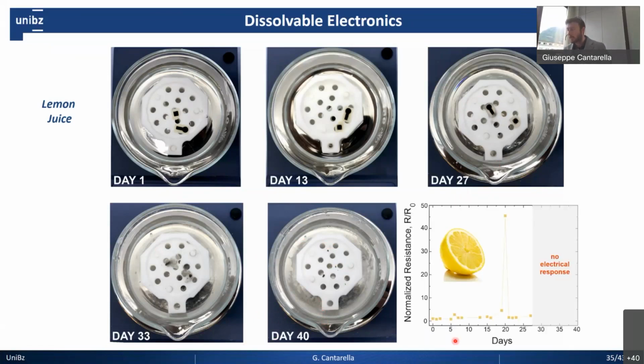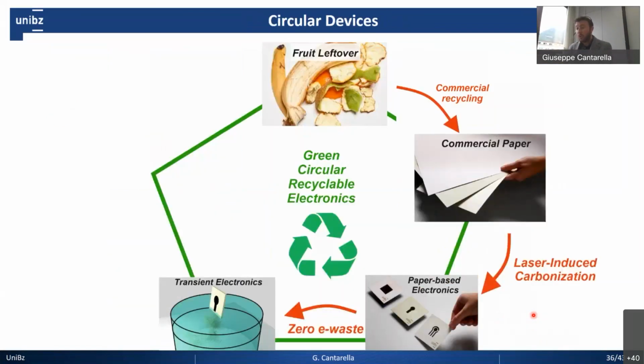We also collected the resistance of this electrode as a function of days, and apart from this peak here, which was due to damage of the contact, the resistance was pretty much constant until 27 days, which means that these electrodes could even be used in outdoor activities and still be functional for different weeks. So we showed that our electronics could be even dissolvable and transient.